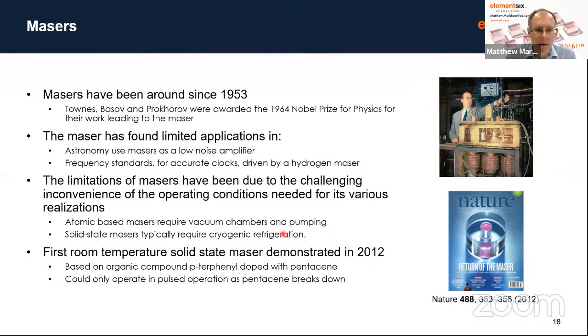However, the great work at Imperial, they developed for the first time a solid state maser in 2012 based on an organic compound called pentacene. But the issue they found is that because it's an organic compound and you need to pump it quite hard with light to get it to maser, it breaks down. So they could only ever run it in a pulsed mode.